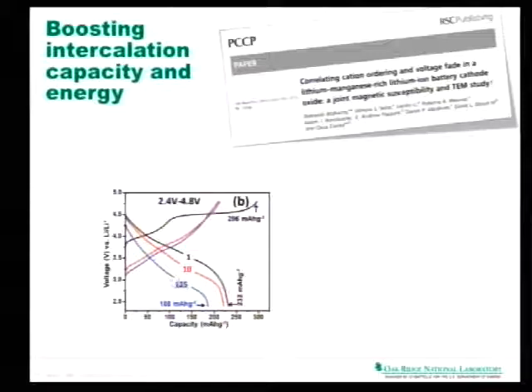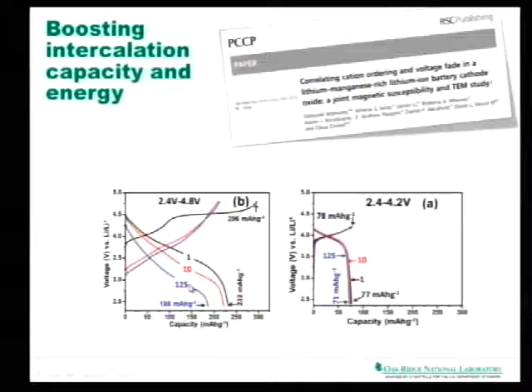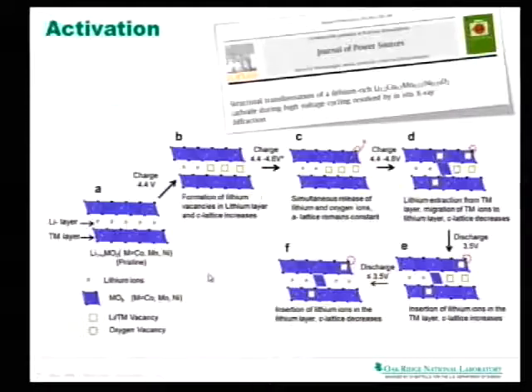Now, if you're going back to the 125th cycle, you're taking your 3 volts there. You're actually there, let's say, maybe about 70 or maybe only 60% depth of discharge because your entire voltage curve is lower than before. So since we're probing voltage in batteries to understand the state of charge, that's not possible here anymore. Now, you can avoid that very, very easily. If you don't charge it up very high, you will never see that fading mechanism, but it's also a battery you cannot use. This is horrible in terms of capacity compared to what we have nowadays. So there's no way around this plateau where we have that problem.